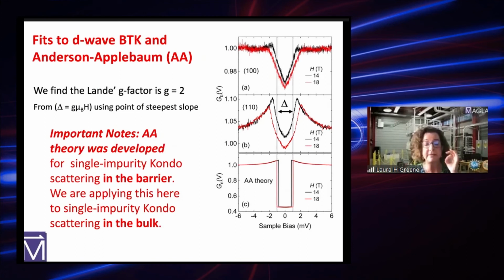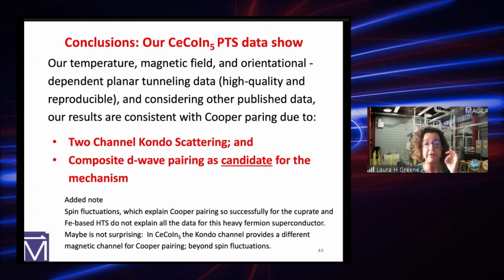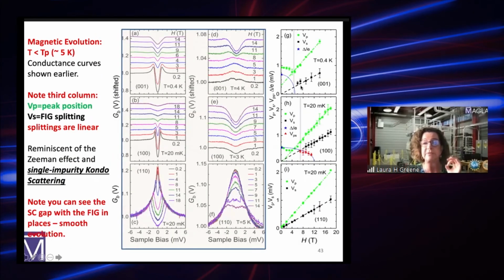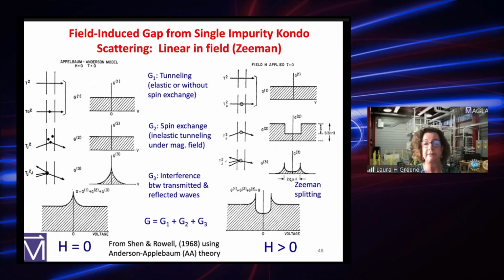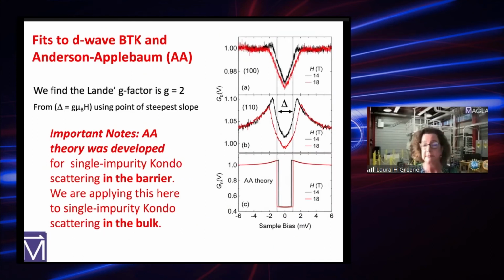So I guess one thing I want to show you that was surprising in our data, which I jumped over very quickly, is that the splitting occurs linearly with field. Up to 18 Tesla that we've measured, the splitting was absolutely linear. And that's why we went to this Kondo scattering, because Zeeman splitting is linear with field. So this is our cartoon.